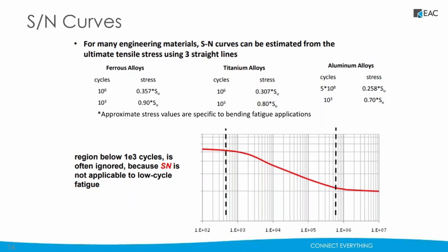And that's perhaps true for their particular product set. But really what makes more sense, if you're just going to do a back-of-the-envelope approach, is to compare it to ultimate tensile strength. That's what fatigue endurance limits are proportional to. Not yield strength. So if you harden a material, the yield strength changes dramatically, but the ultimate tensile strength doesn't. And you'll find similarly that you can harden a material, change the yield strength, but you're getting roughly the same fatigue performance out of that material. So switching over to, at a minimum, ultimate tensile strength rather than yield is maybe your first step towards improving a very quick approach to fatigue evaluation.